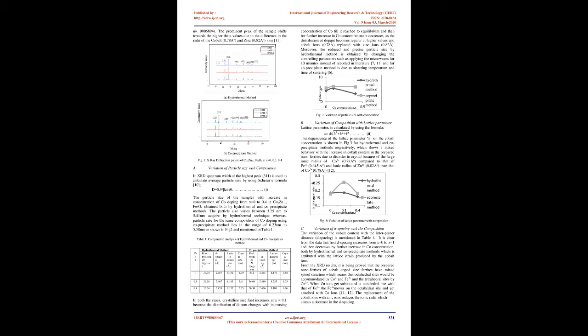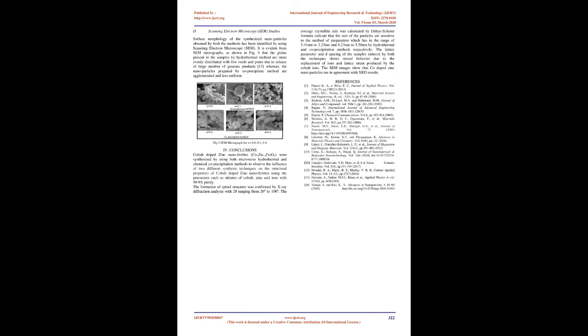The particle size varies between 3.25 nanometers and 5.41 nanometers by the hydrothermal technique, whereas the particle size for the same composition of co-doping using the co-precipitate method lies in the range of 6.23 nanometers to 5.58 nanometers, as shown in Fig 2 and mentioned in Table 1. In both cases, crystalline size first increases at x equals 0.1 because the distribution of dopant changes with increasing concentration of Co till it reaches equilibrium, and then for further increase in Co concentration it decreases, as the distribution of dopant becomes regular at higher values and cobalt ions, 0.78 Å, replace zinc ions, 0.82 Å.